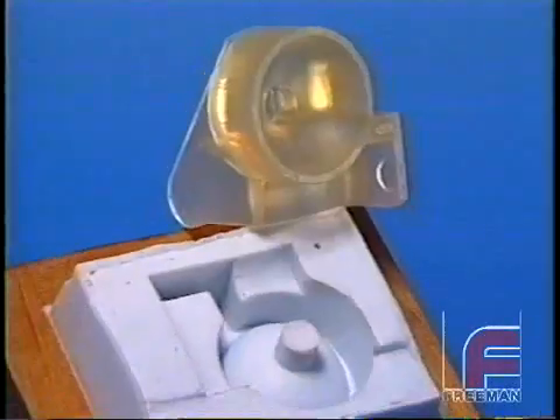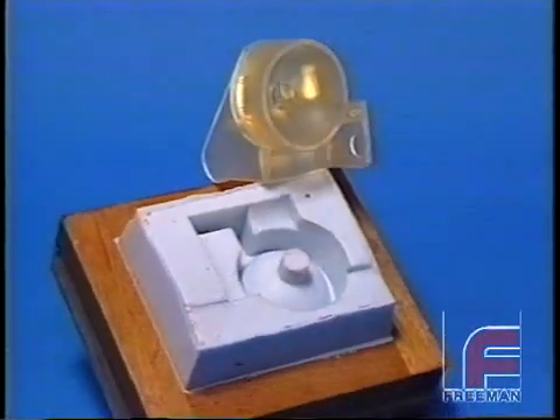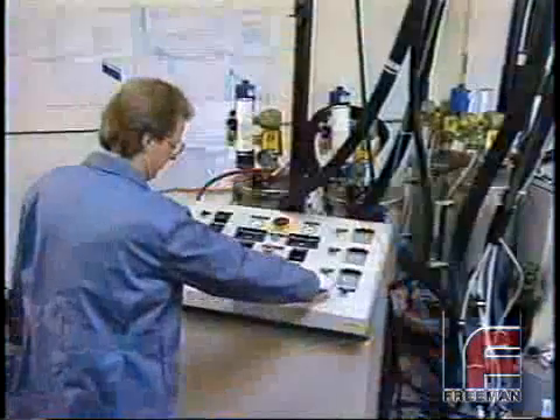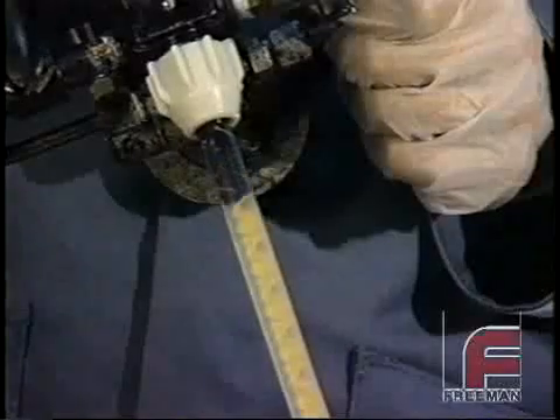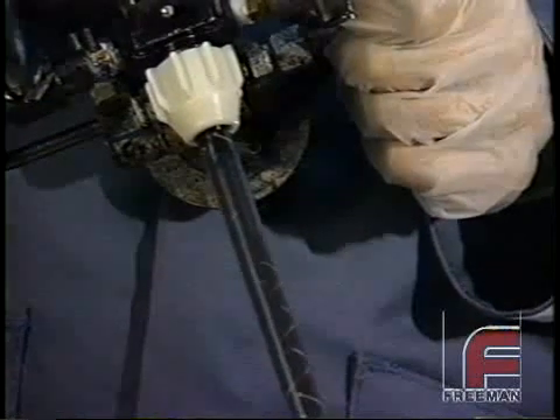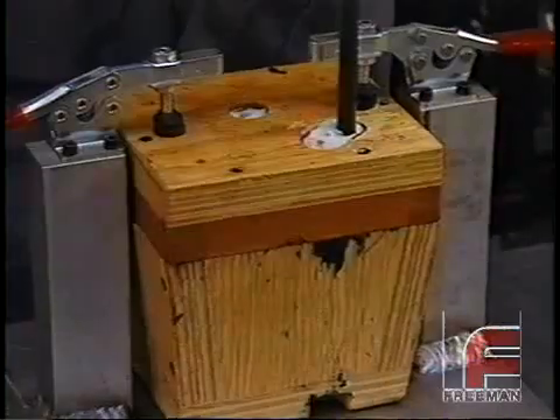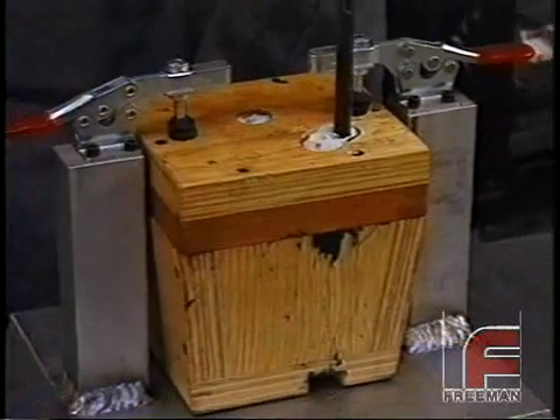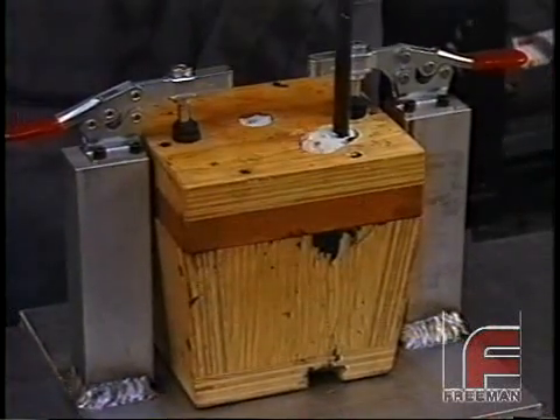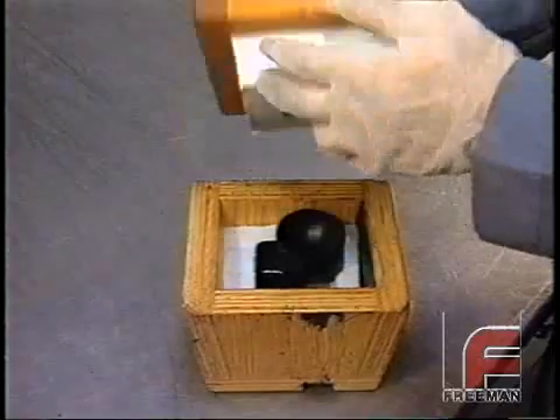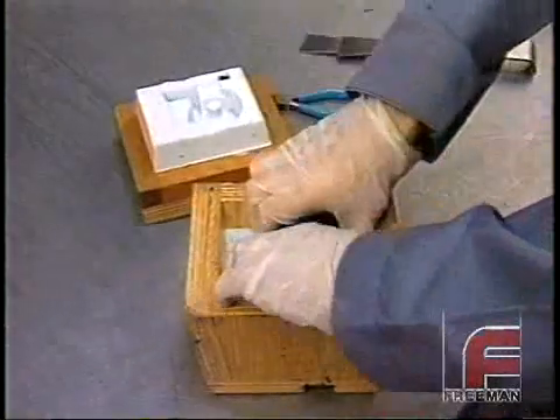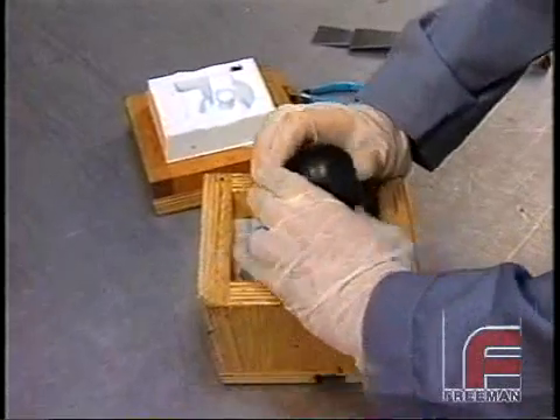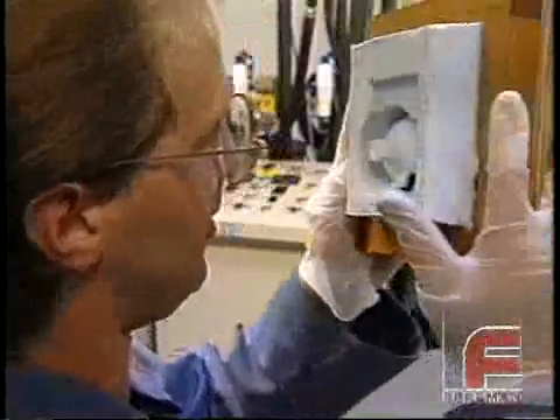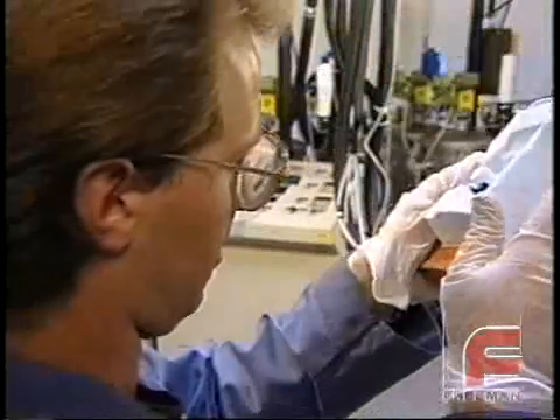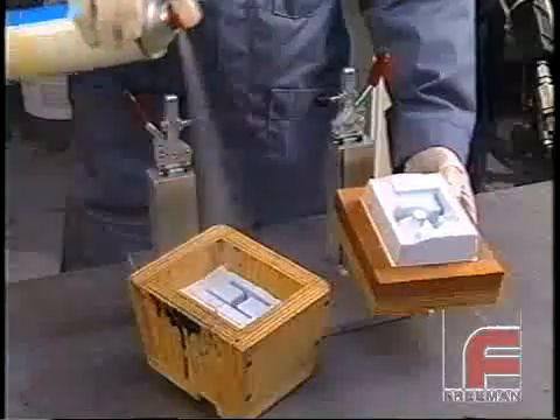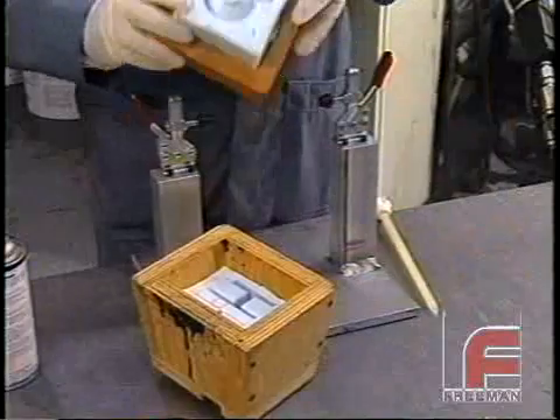A hand-finished stereolithography master is used to produce a silicone mold. The Parts in Minutes resin and hardener are then mixed to precise ratios in a meter mix dispense machine and injected uniformly into the mold, assuring high-quality parts that are virtually void-free. The part hardens in just seconds, and after a few minutes, it's ready for demolding. The fast gel time reduces leaching into the silicone mold, extending its service life. After a brief setup, the mold is ready to cast more parts.